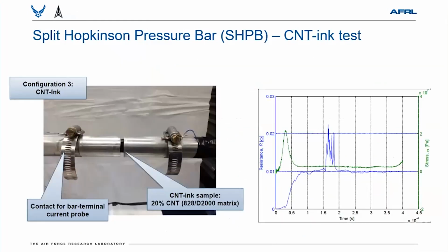So after all this, we made some materials without functionalization. Then we tested them. This is the moment of truth: split Hopkinson bar pressure test, high impact, high g testing. And we found that with this CNT mesh optimization on interface design and putting it in polymer, creating a CNT ink, this material survived the high impact scenario, whereas without modification, we didn't get any signal.